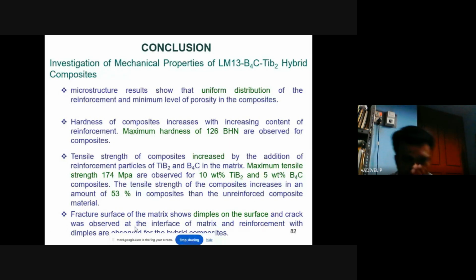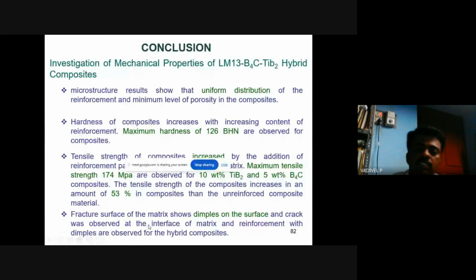The tensile strength is increased by the addition of ceramic reinforcement. The maximum tensile strength obtained is 174 megapascal, for 10 weight percentage of TiB2 and 5 weight percentage of boron carbide. The tensile strength of the composite increases by 53 percentage compared to the unreinforced composite material. The fracture surface of the matrix shows dimples on the surfaces, a crack was observed at the interface of the matrix and the reinforcement, and dimples are observed for the hybrid composites.